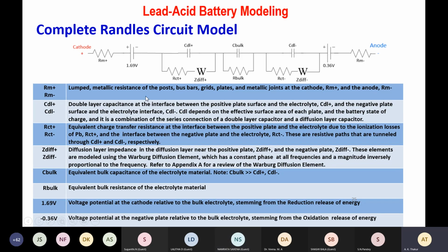If we look at the two ends, at the cathode and current collector and the anode and the current collector, we have a resistive barrier, and this is known as lumped resistance, Rm plus at the cathode end, Rm minus at the anode end. And this lumped resistance arises because of the metallic current collector's bulk resistance, and all the lead wires and plates that are metallic, they join and their resistance has to be added together both at the cathode and the anode. So this is known as electrode resistance at the interface of electrode combination with the metallic current collectors.